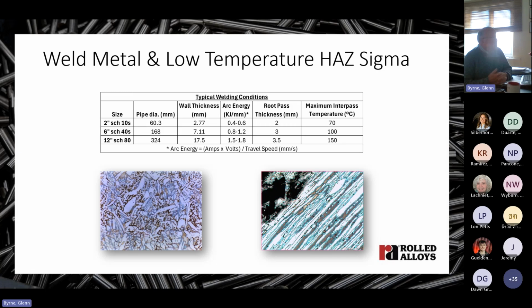And this corresponds with the nose of the CCT curve that I showed you in the earlier slide where sigma forms fastest. Now, thin wall pipes with only two-dimensional heat flow tend to be more prone to this problem than thicker pipes. The issue really is conducting heat of the weld thermal cycle away from the joint as quickly as possible to avoid the nose of that sigma phase transformation curve.